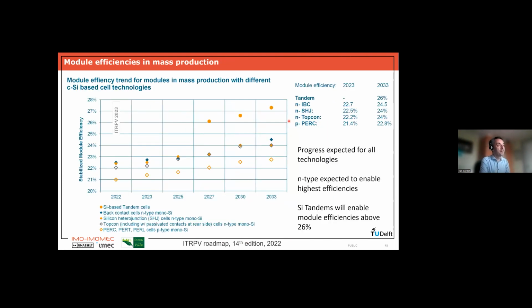And then finally, the module efficiencies. These are, again, the best-in-class module efficiencies that we have today. For PERC, we are around 21.5% module efficiency. For the passivated contacts, it's above 22%, and the highest module efficiencies are typically for the IBC modules, for instance, the SunPower ones, which have efficiencies of even close to 23%. Again, in the next 10 years, a lot of progress is expected for all the technologies. But in the end, the module efficiencies for single junction devices will be limited to 24.5%, perhaps 25%. If we want to go higher than that, again, we will need to go to silicon tandems.